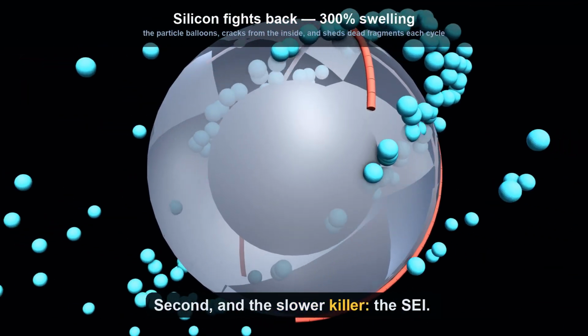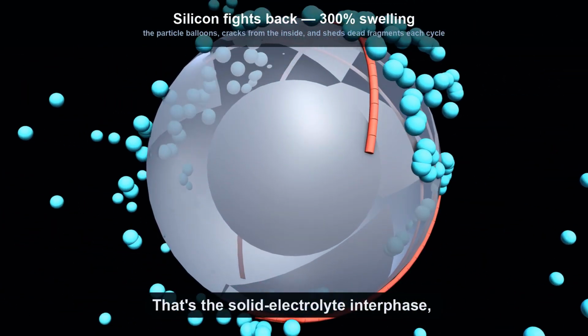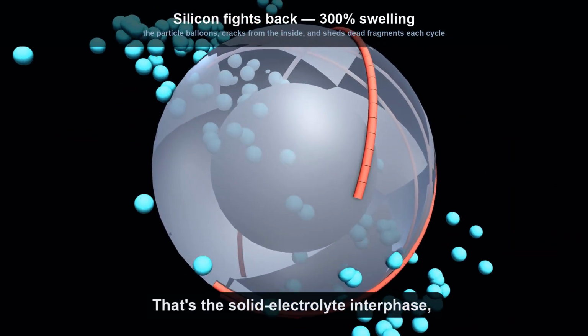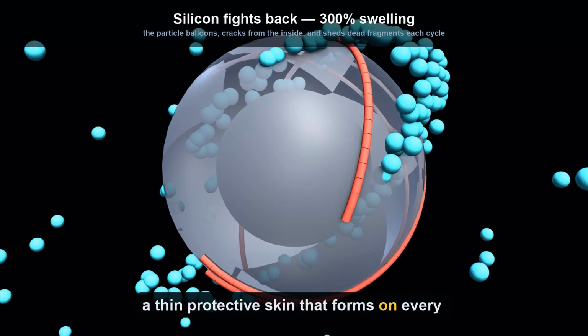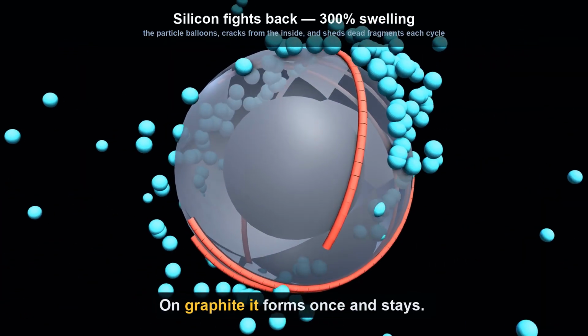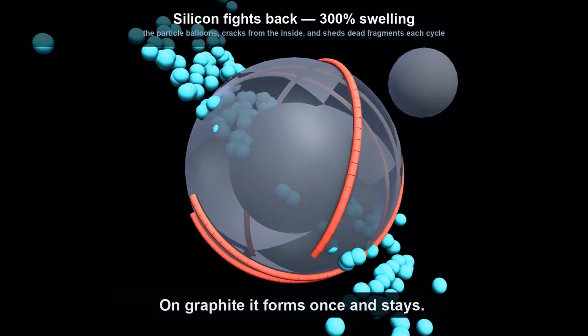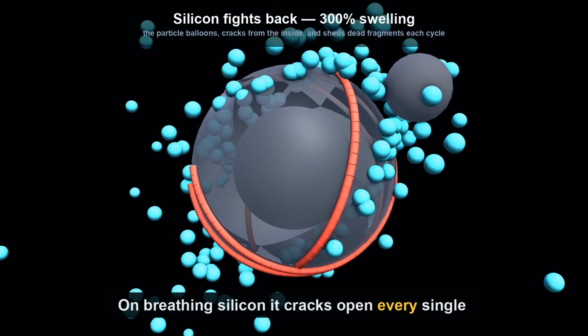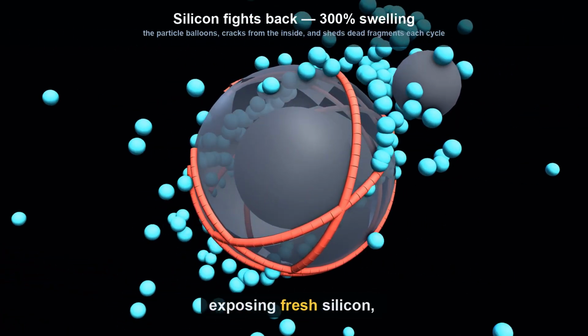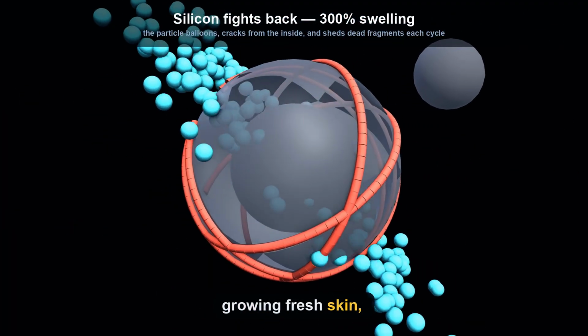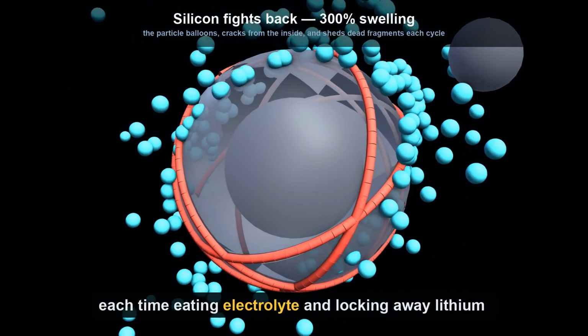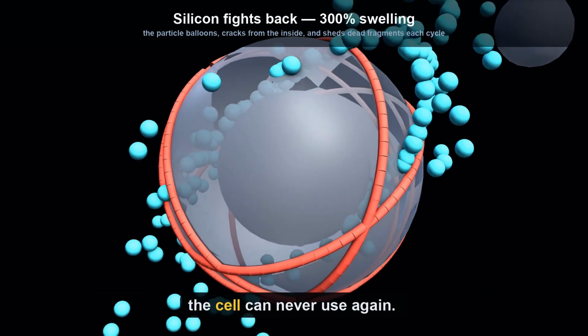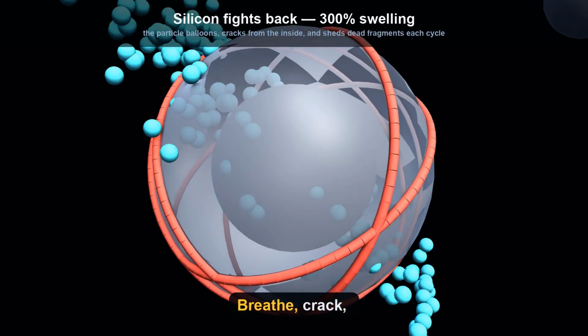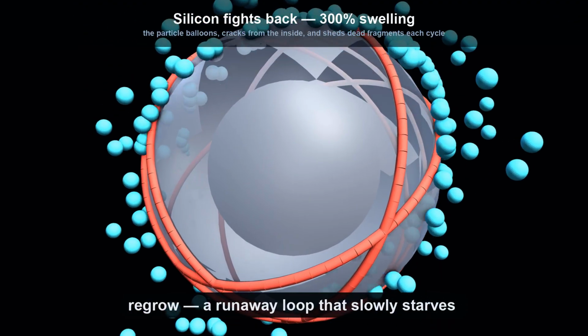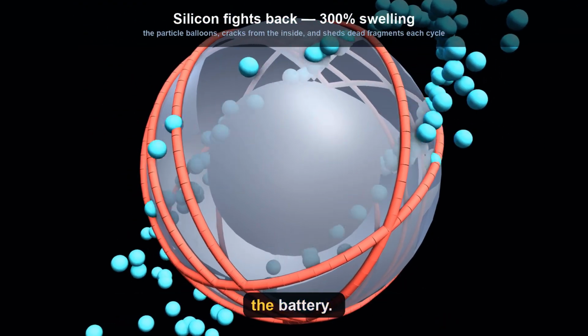Second, and the slower killer, the SEI. That's the solid electrolyte interface, a thin protective skin that forms on every anode. On graphite, it forms once and stays. On breathing silicon, it cracks open every single cycle, exposing fresh silicon, growing fresh skin, each time eating an electrolyte and locking away lithium the cell can never use again. Breathe, crack, regrow. A runaway loop that slowly starves the battery.